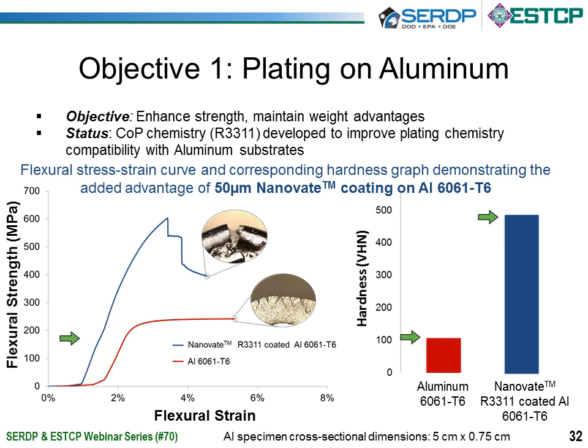And then we did a flexural test on an aluminum bar coated with just 50 microns of the nanostructured cobalt alloy. And what you see in this is a tremendous increase in the flexural strength of the aluminum substrate just simply by putting a 50 micron coating on. So that demonstrates that potentially there is room for enhancement of properties with the nanostructured coating.